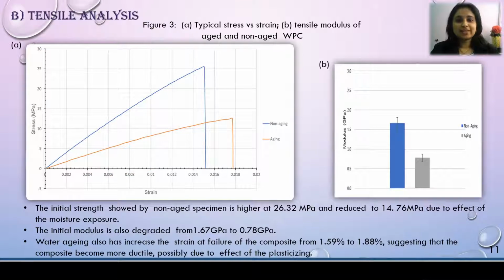Moving on to the next analysis, which is tensile analysis. This graph shows the stress versus strain curve of aged and non-aged specimens. From the graph, the initial strength shown by the non-aged specimen is higher at 26.32 megapascal and reduced to 14.76 megapascal. This is due to the effect of the moisture exposure.